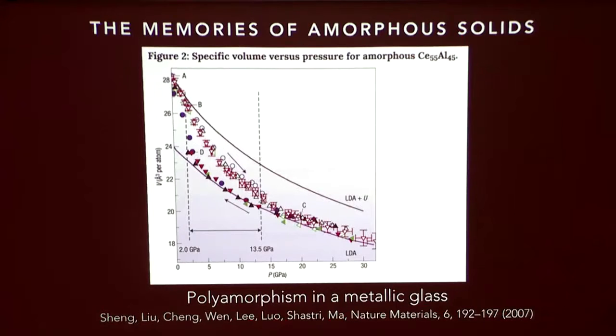This was an experimental and computational study done by Howard Sheng, Evan Ma, and some others. What they're showing is that this is a glass in which you have a phenomenon called polyamorphism. Basically there are two distinct amorphous structures that can be formed in this glass, and you can switch between the two, in this case by imposing pressure. You have one high-density amorphous phase and a low-density amorphous phase, and by applying pressure, you can cause a transition between the two amorphous states. So even though we find it difficult to characterize the structure of the glass, it's possible you could create a single glass, a single composition, and have regions that are in different states, and thereby you could store information.